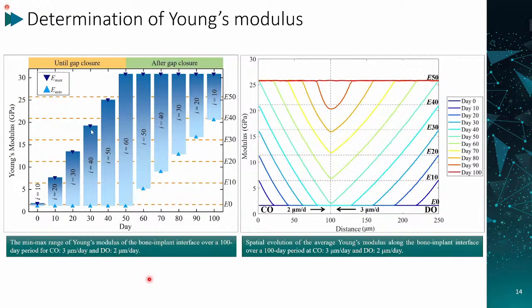So here shows how to determine the Young's modulus for this spatial and temporal evolution model. As we can see, at day 0, it's a minimum Young's modulus state, and after 10 days, because the CO and DO fronts get close to each other, they become stiffer and stiffer. So until day 50, the CO and DO fronts fronts meet each other. At the two ends, they already reach the highest value of Young's modulus. This we call before closure. After the gap closure, the lowest parts become stiffer and stiffer. So the average Young's modulus reaches the maximum state after 100 days.